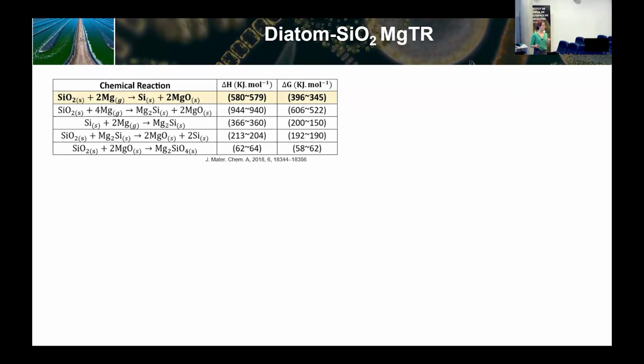Of course, it's not as simple as one reaction, because normally this will be the reaction that should be taking place. But normally you get a lot of extra reaction products like magnesium silicide and magnesium silicates. There is not much research into this, but it is believed that this reaction is so exothermic that it will trigger other reactions to happen at different particle places. Some of them will happen more at the interface, some more in the material, and so on. So we have to be super careful when we do the synthesis of the material.